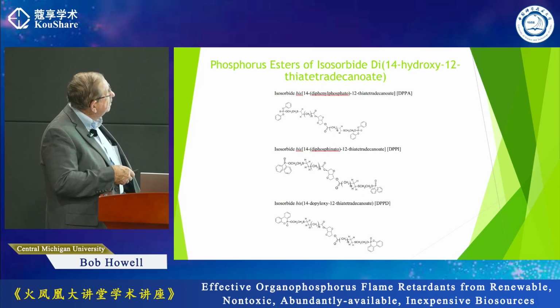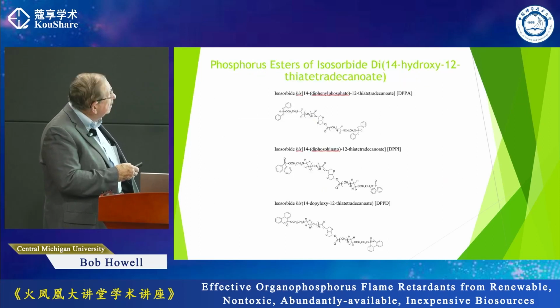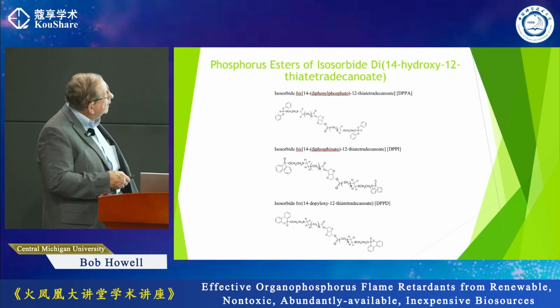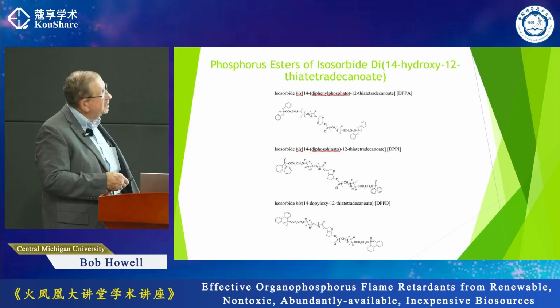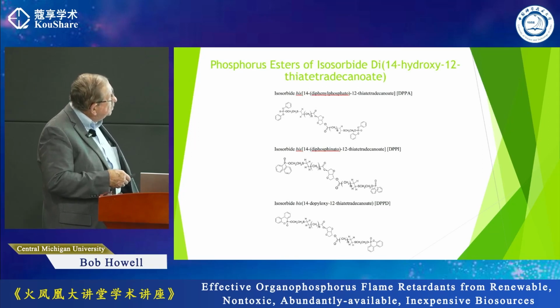And here's a series of the first set. Start with isosorbide, esterify with undecenoic acid, which you get from pyrolysis of castor oil. And that gives you terminal double bonds. If you do thiol-ene reaction with 2-hydroxyethane thiol, that generates hydroxyls at the terminal positions, which then you can make esters and get active species.